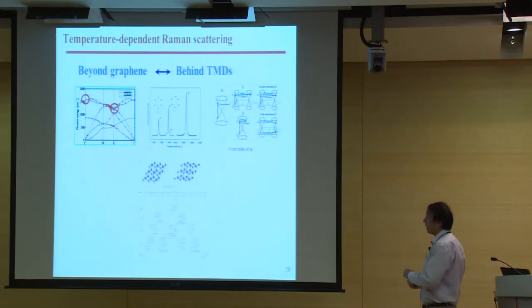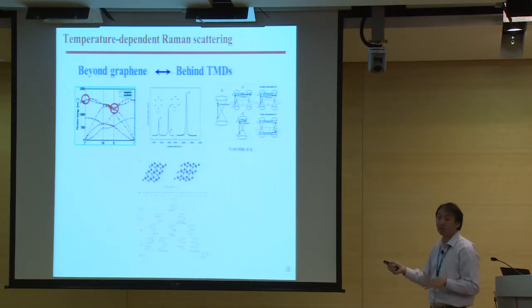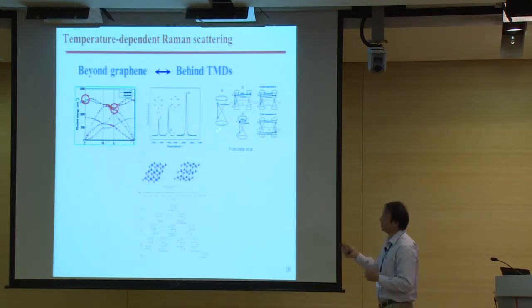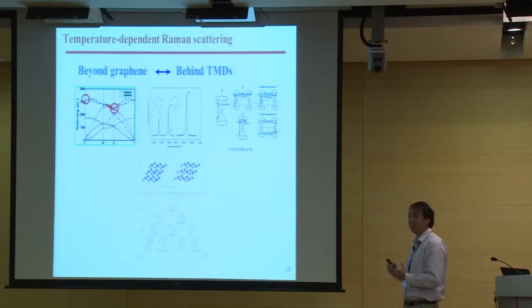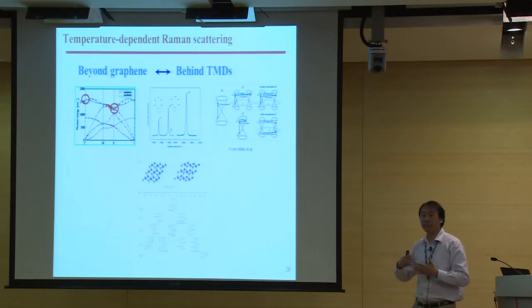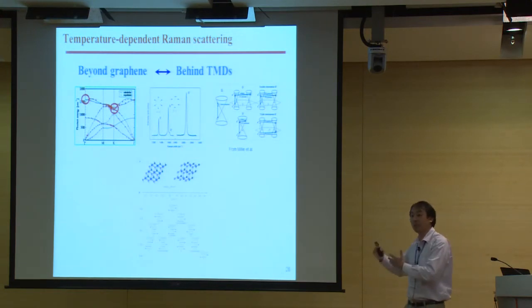Okay? And the good thing about Raman for the study of graphene or even carbon nanotubes is that the G or 2D or G prime is in resonance with the electron. For example, this one is a very famous inter-valley double resonance. That's why the Raman signal of either G prime or the defect mode is in resonance, and the signal is extremely strong. So we can easily record a Raman signal, and through the strong electron-phonon coupling, we can probe the electronic property or band structure of graphene.